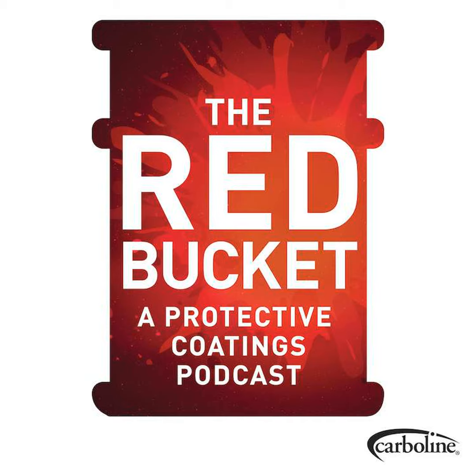Yeah, no doubt. Fluoropolymers excel as top coats, right? As far as UV protection, color and gloss retention, there are none better. However, fluoropolymers only work when we look at something, let's say like a water tank, they only work because they are part of a full system, right? So coating systems made up of primers, one or more intermediate coats, top coats. Okay, so we use the primer. Obviously, it provides adhesion to whatever substrate that you're working on. In this case, we're obviously talking about steel. So depending on the type of primer that you use, you can have some other forms of protection. With zinc primers, you get galvanic protection. With epoxy primers, you get barrier protection. Or if you combine moisture cured urethane or epoxy resins with zincs, you get the benefit of both.